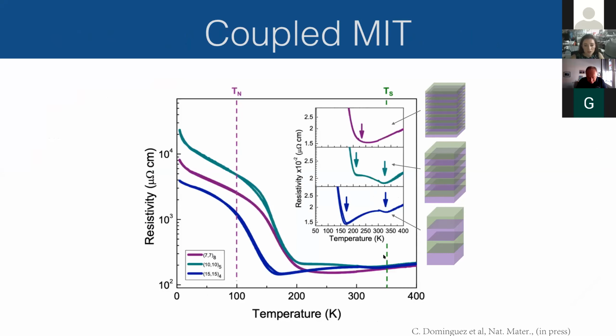So what comes out is perhaps to begin with not super surprising. So when the layers are very thick, so we have a high lambda, you have two different transitions. So one that looks a bit like samarium nickelate at high temperature, and one that looks a bit like neodymium nickelate at lower temperature. And then as you make the layers a bit thinner, the temperatures of the transitions come closer together, and then finally you just have one transition for thin layers, so low lambda, and there's not even a suggestion anymore of a high temperature transition.